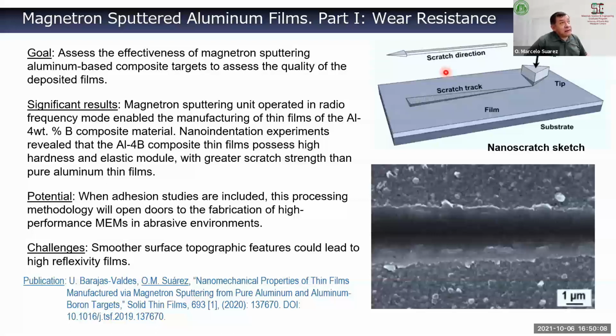So we looked around and we saw, well, we own a magnetron sputtering unit that is housed in our class 100 clean room. And we had purchased a nano indenter something like 3 years before that. So we said, well, let's see, we can try that. We started depositing aluminum as a reference, pure aluminum, on glass slides and silicon wafers. And then we used our composite, that aluminum matrix composite, as target in our sputtering unit, and started comparing the results between both.